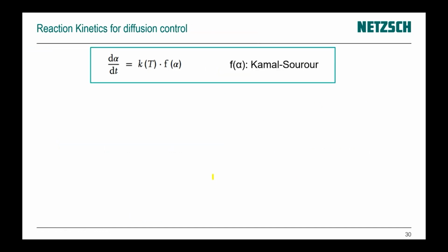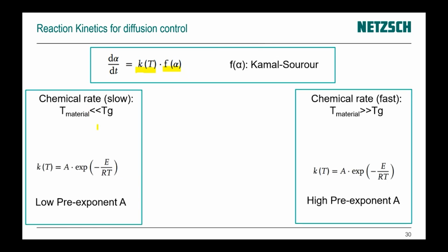What is inside our software? Here we have a dependence on temperature and the reaction type, which is Kamal-Sourour. If we are much below glass transition, then we have the Arrhenius equation with a low pre-exponential factor A. If we are much above glass transition, then we have again the Arrhenius equation, but with a high pre-exponential factor, and the same activation energy, which depends on the nature of our material.